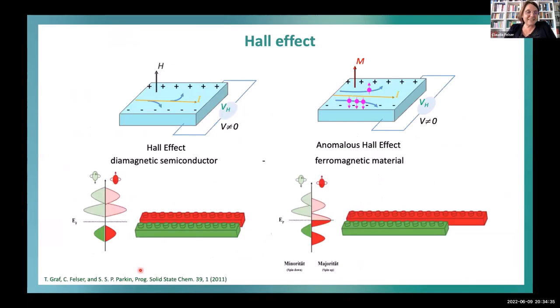So, but at the end, it's nice to have some interesting exotic topological quantum effect where you see something interesting at low temperature, but we are in spintronics, we want to see something in real life and at higher temperature. So a very nice measurement, which everybody can do, and we also, because we have a PPMS, is a Hall measurement. So we do a voltage measurement with an external magnetic field. If we have a non-magnetic compound, this is a typical Hall measurement, and we get more information beyond what we get in a normal resistivity measurement. We learn about the charge carrier concentration, we learn about the type of charge carriers, we can see even the mobility. And we are nowadays even able to make such good high quality crystals that we very often see quantum oscillations and even see the Fermi energy in this material.